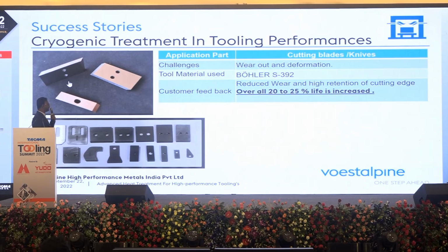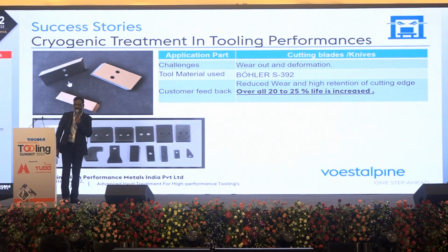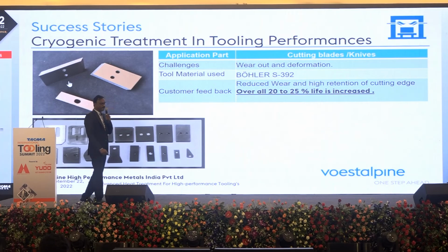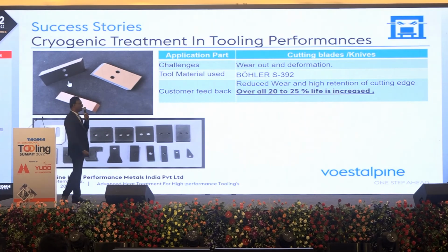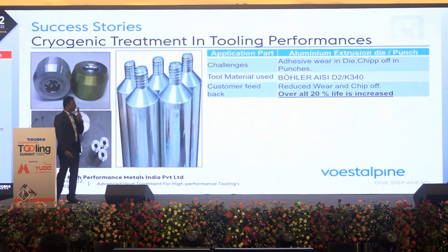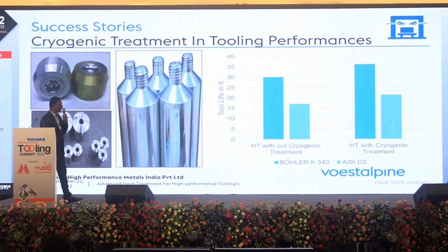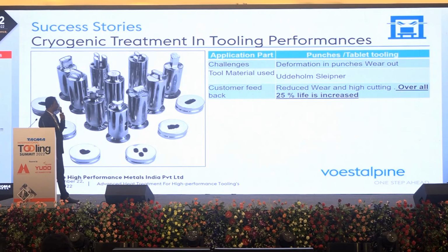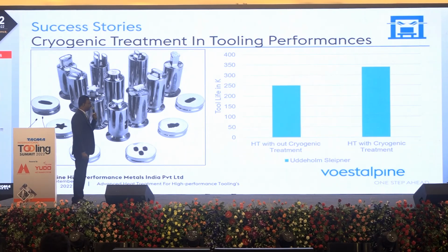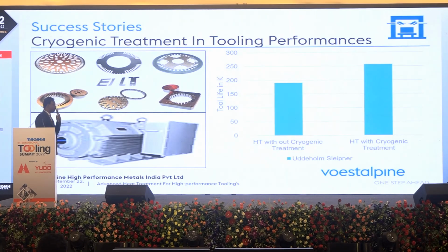Same thing for the cutting blades and knives for a different customer. Here the powder metallurgical version of BÖHLER S392 will always give additional performance at the raw material stage as well as when it is properly heat treated. And when we do the cryogenics, it has improved performance by another 20 to 25%. Of course, aluminum extrusion dies also have a good case study comparing AISI D2 and K340, which are around 25 to 30% performance. And for tablet tooling, the emerging segment nowadays, they are making attempts with new premium grades, BÖHLER K340, Uddeholm Sleipner. So these materials will really improve the performance when they do proper cryogenics. There is also 25% in the stamping tools by using Uddeholm Sleipner.